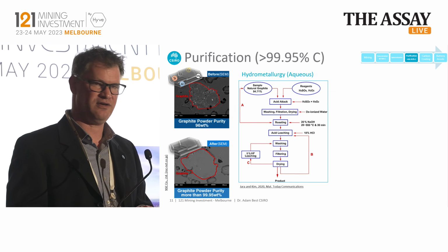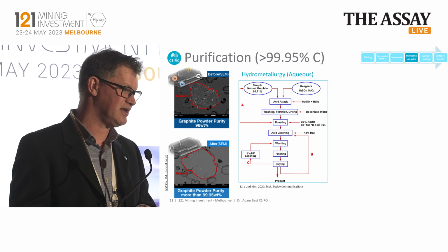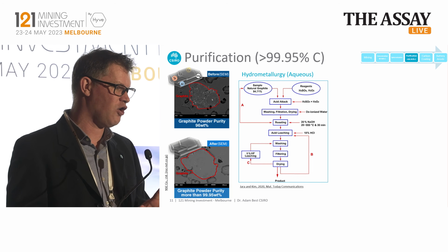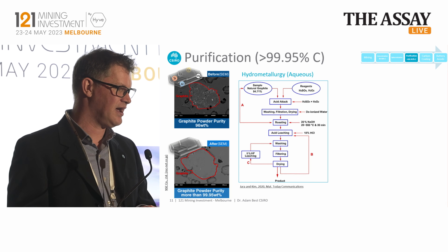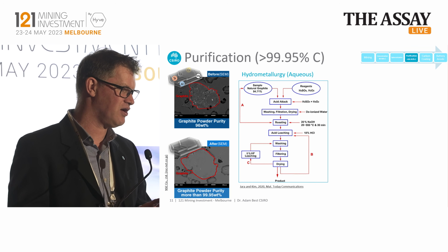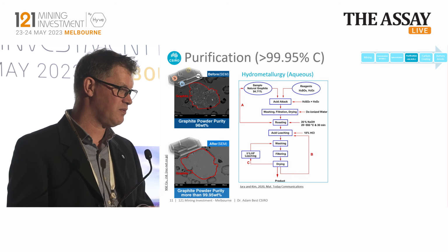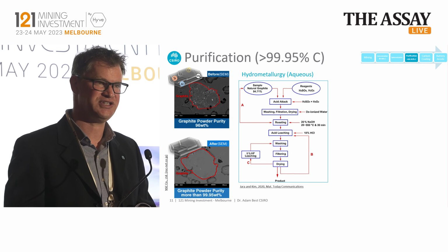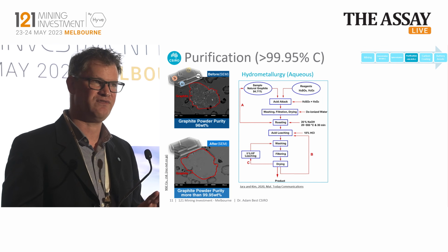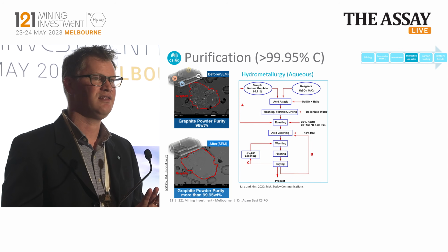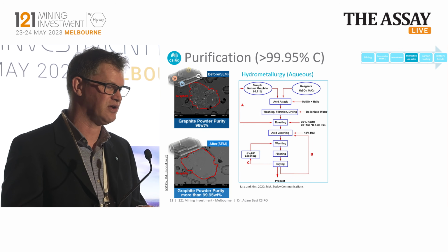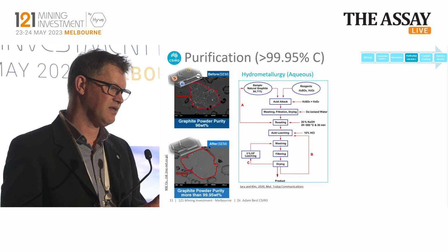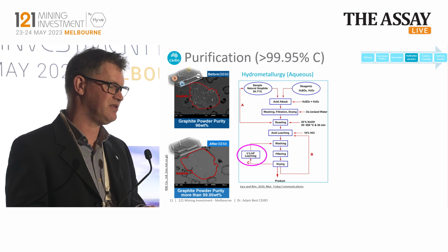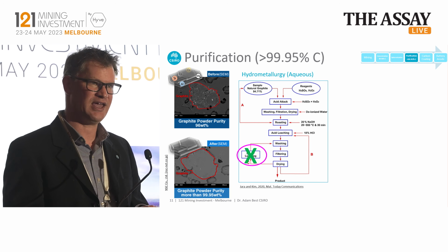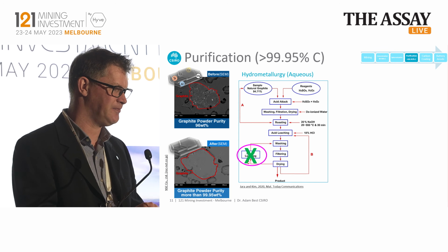So there's plenty of ways you can do this. There's hydrometallurgy, and as you can see here, there's a whole range of tests that we can do. You can do things such as using sulfate and peroxides and deionized water to wash out those impurities. The other one that you'll see here on the bottom left-hand corner is HF leaching. This is generally only done in China because it's really hard to dispose of HF. And for any of you who understand HF, this is as toxic an acid as you can get. If you get this on yourself, you're in a lot of trouble. It's not something that you should play around with. So we've been working quite hard on developing new processes which are cleaner and greener and getting rid of that HF step.